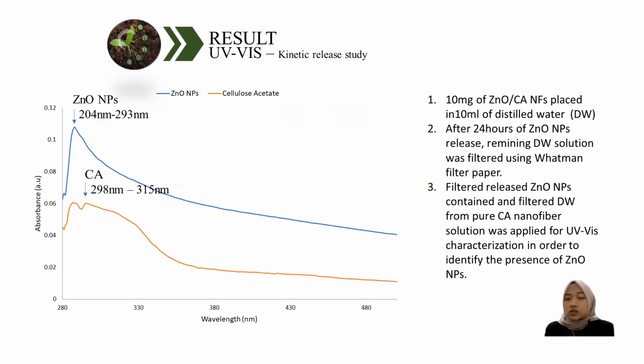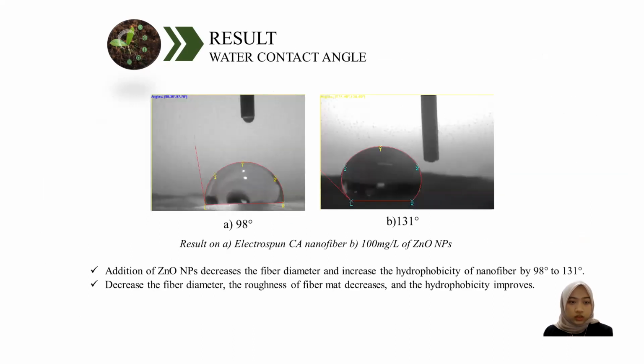The UV study is to study the kinetic release of the zinc oxide nanoparticles from the nanofiber. We immersed the nanofiber for 24 hours, and the result shows that the zinc oxide nanoparticles within the fiber are able to be released within 24 hours.